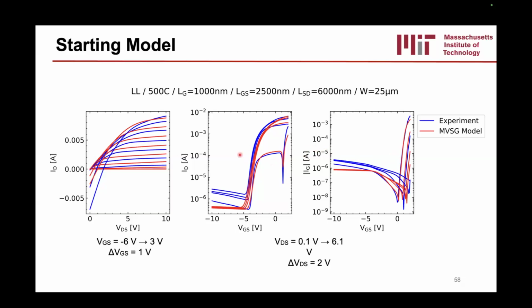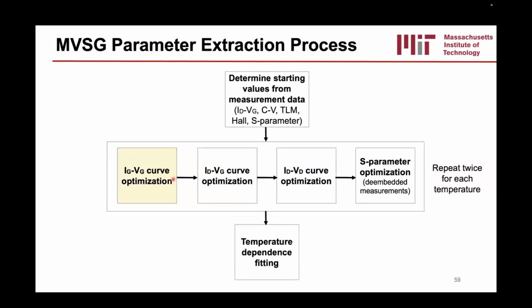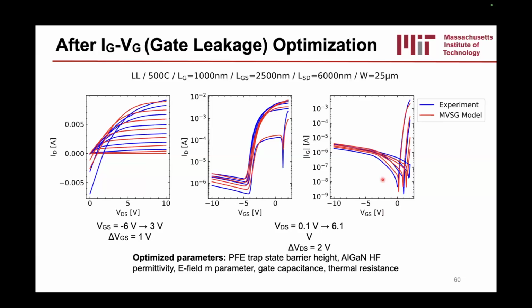What we can do then, though, is use an automated extraction process using Python and GSpice, where we can optimize various parameters over these curves multiple times. So in this case, we can optimize the gate parameters associated with, for instance, the Schottky barrier height, the Poole-Frenkel emission, the thermal resistance, and the gate capacitance. And we can get a very good fit to the gate leakage characteristics, although not as great a match to the transfer and output characteristics.